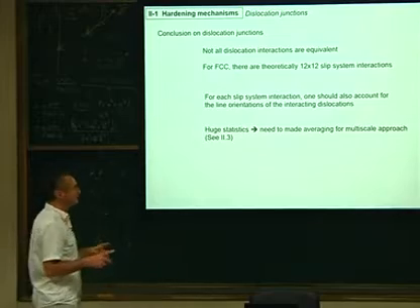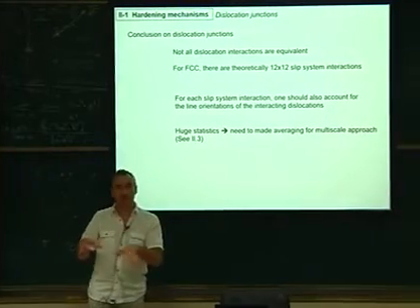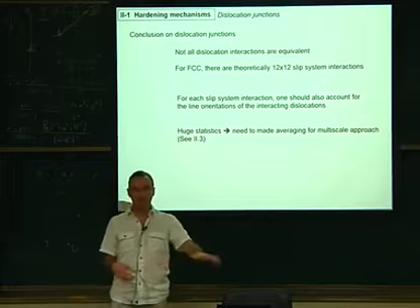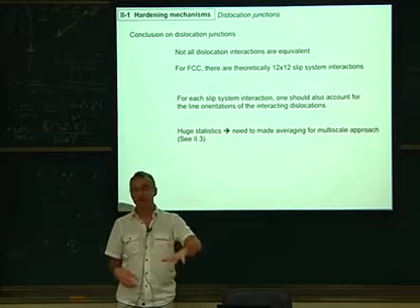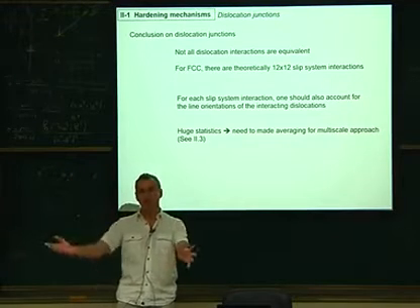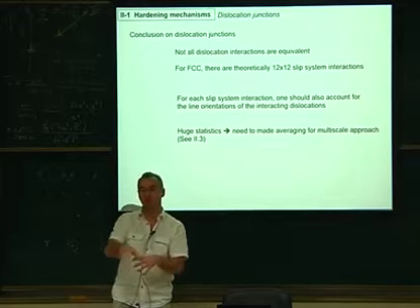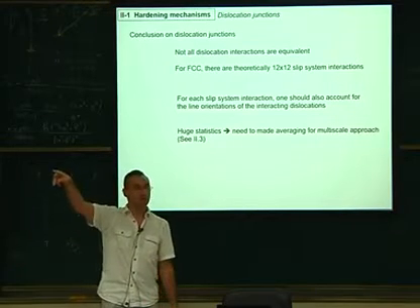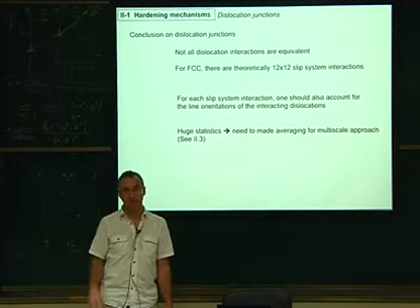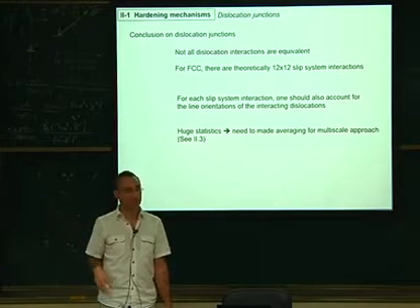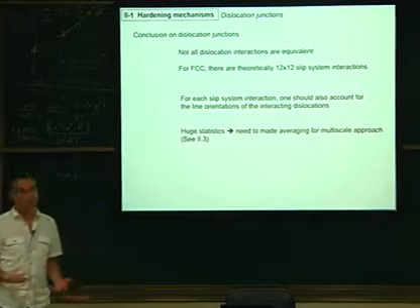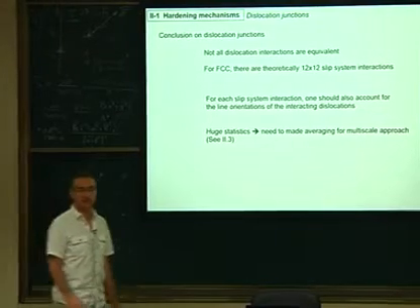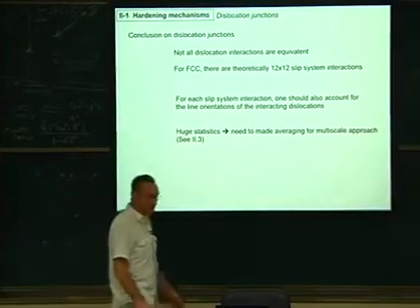I don't know if I was clear, you see. You put many dislocations of a given system with all possible orientations, and another possibly random spread of dislocations on another slip system, and you let them move. So you measure how much stress you need to push in order to pass through the forest dislocations, and this gives you an average value for the strength. You have tau versus dislocation density. And this is how people measure this matrix. Okay, and tomorrow I will show you that for the crystal plasticity model, for junctions.